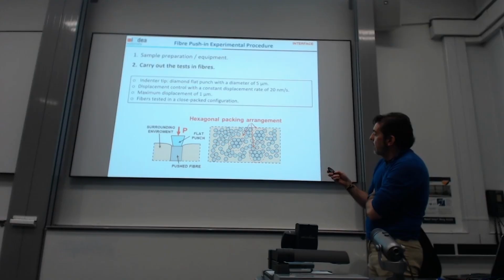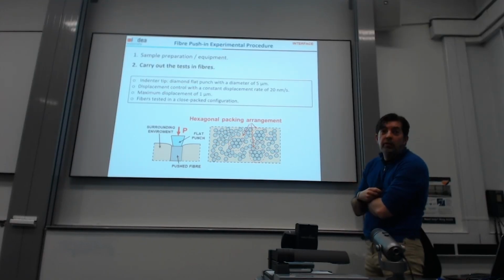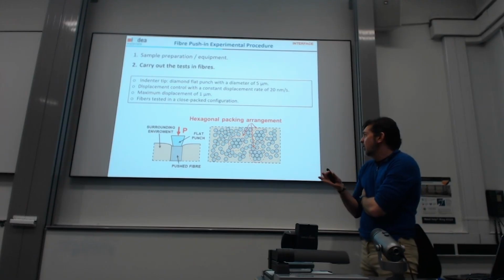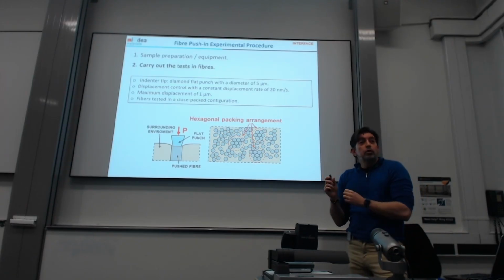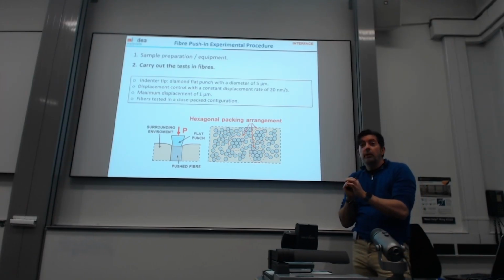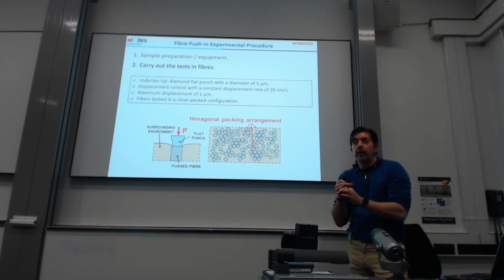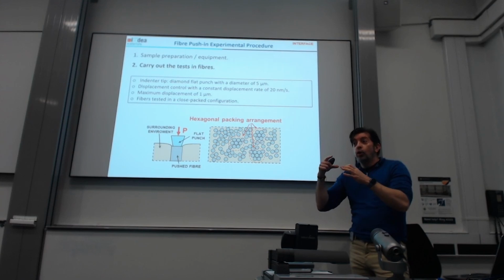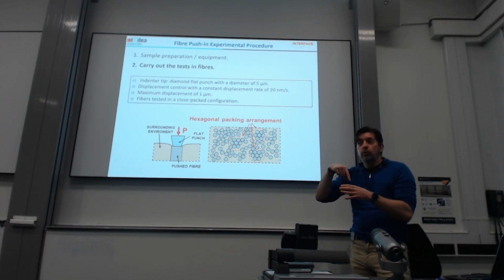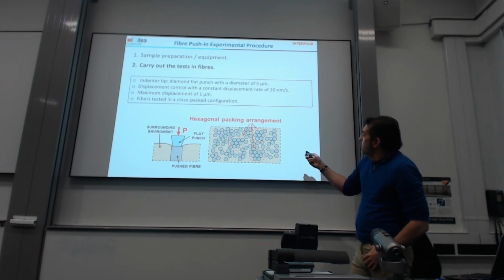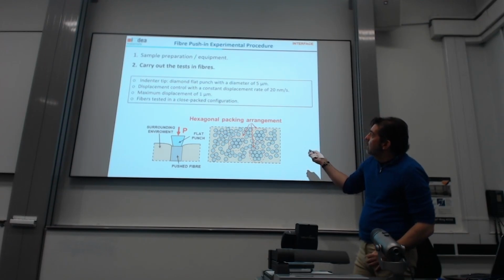Some of the experimental details: we use a flat punch with a 5 micron diameter. The fiber is around 6.5 microns, so you need a punch with a diameter which is close to the fiber. And I will tell you why now. You cannot use a 1 micron punch to push into a 5 micron fiber, because you are going to cause plastic deformation. So we use a displacement rate of 20 nanometers per second, with a maximum displacement of 1 micron.